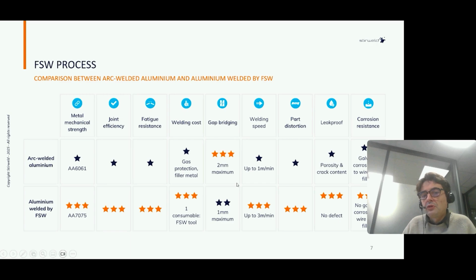Now, the main problem of friction stir welding is the gap bridging. With arc welding, we feed the material, we add wire. So this wire feeds the gap between the parts. And so we don't have material feeding in friction stir welding. So the maximum gap is 2 mm for MIG welding, while it is maximum 1 mm in friction stir welding.